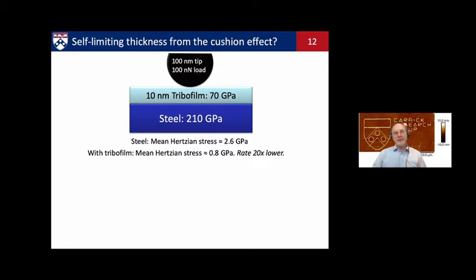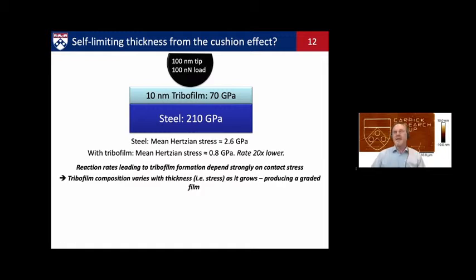We think that this stress-activated growth is the key explanation for why the growth drops off, why it attenuates with time, why it levels off at this 50 to 100 nanometers. As the film grows, it is cushioning the stress coming from the tip, the load coming from the tip. The stress reduces, the rate of growth reduces. So that strong dependence on contact stress leads to this leveling off of the growth.